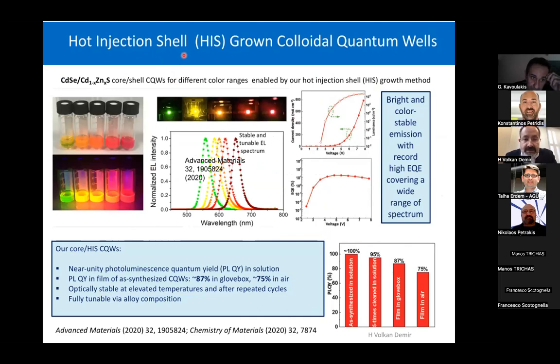And this was particularly important because either we do core shell or we do core crown shell. And at the end, we actually complete the structure with a hot injection shell material. This was critical to achieve high efficiency in terms of quantum yield, but also high stability against increased temperature during operation. And using this technique, in this case, we were interested in developing a cadmium zinc sulfide based shell. We were able to observe very reproducibly high efficiency. This is really limited by our absolute efficiency measurement approach and has been indeed cross-checked with a number of independent labs. It's near unity. We can see it in this mono-exponential decay too.